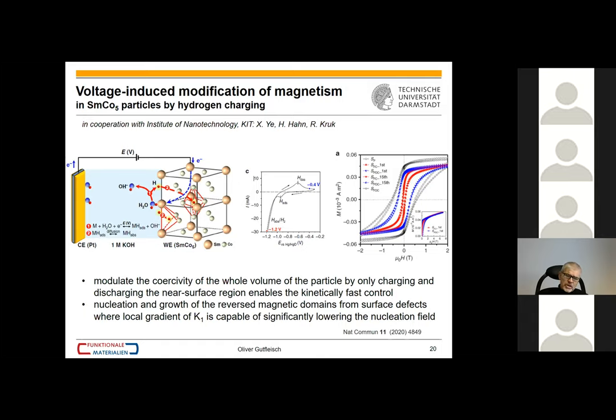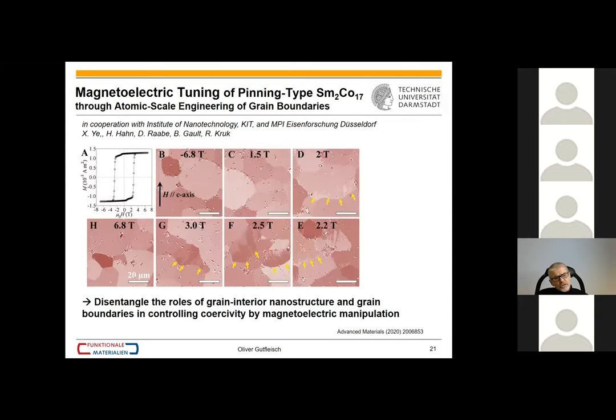Saturation will also be changed, but actually coercivity we change here by more than one order of magnitude. And that is related to the fact, this is a follow-up paper here again with KIT and MPIE. You can see in this mesoscopic or microscopic Kerr imaging that magnetization reversal, we can see it, for example, here nicely, is initiated at a grain boundary in 217.